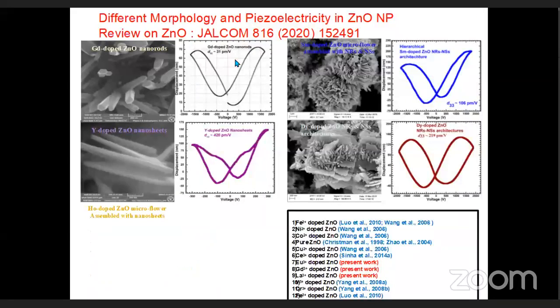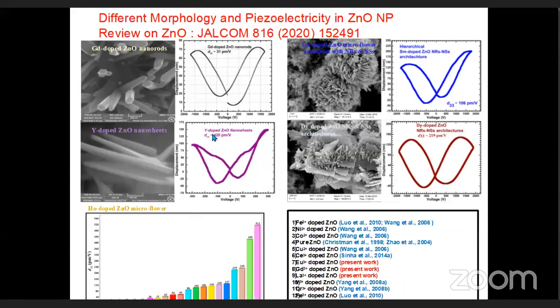Now, this is the one which shows the D33 value. These curves are called butterfly loops, which is a reverse piezoelectric effect, where we apply an electric field, a voltage, and we get a variation in the dimension, the change in the dimensions. This is plotted, and from this we can find out the D33 value, that is the piezoelectric charge coefficient. And in one particular case, the doped nanosheets, they are sheets, not rods, we get a very high value of piezoelectric charge coefficient, even more than 400 picometer per volt.